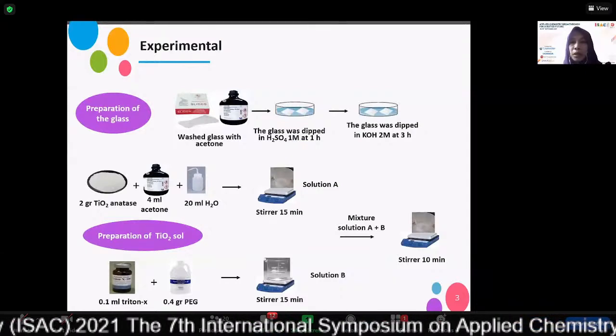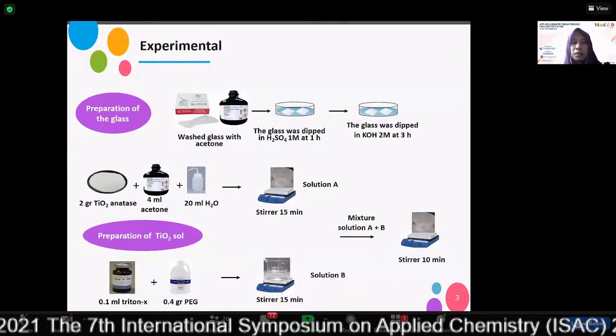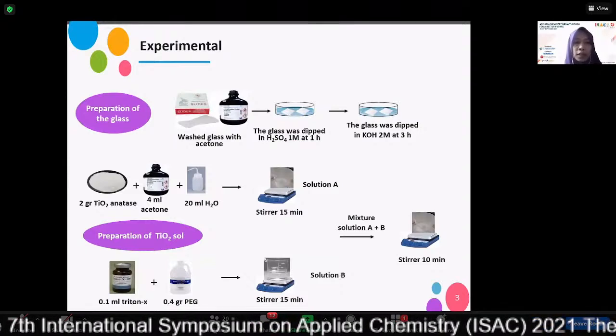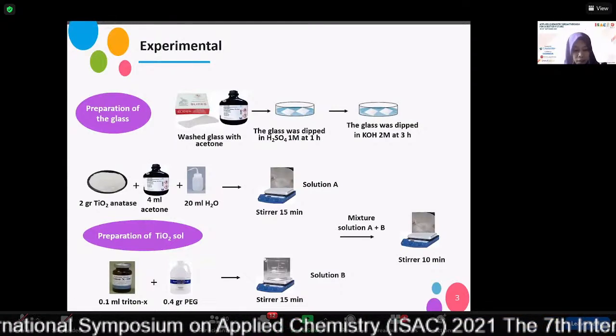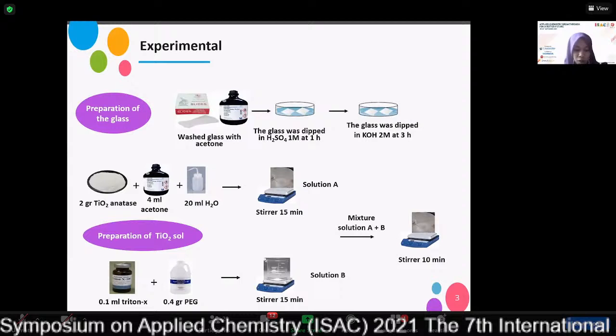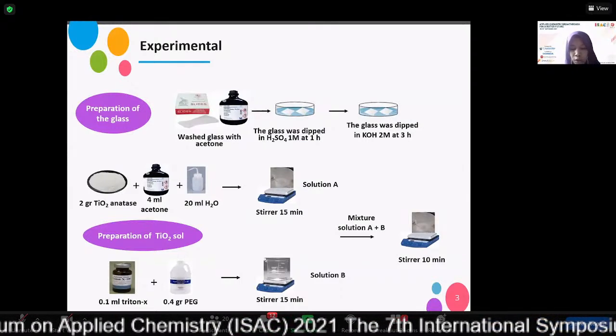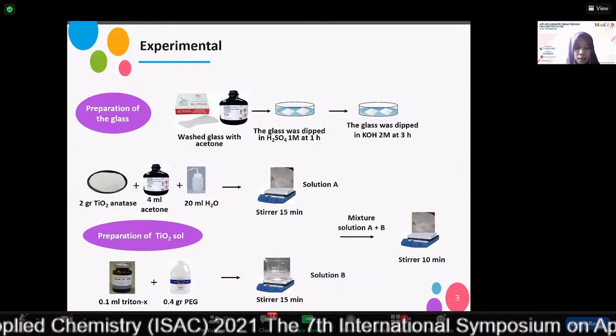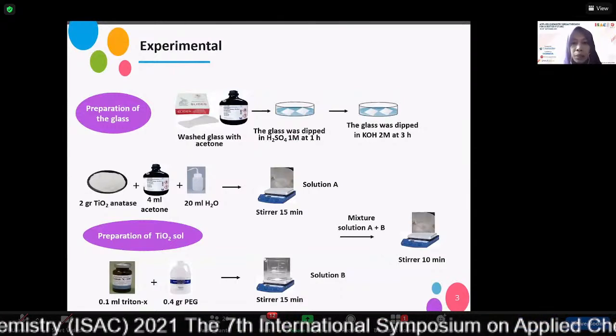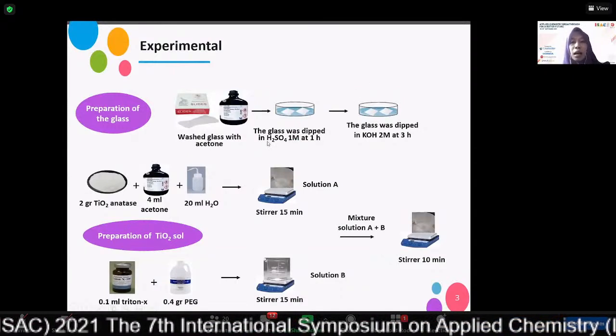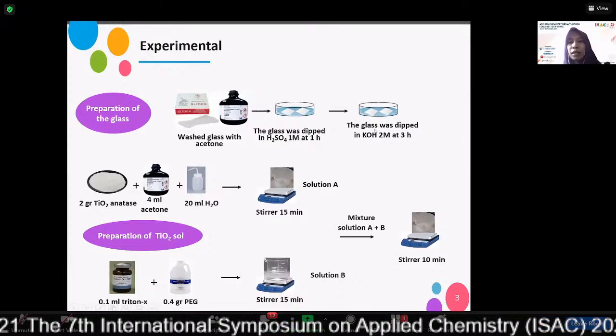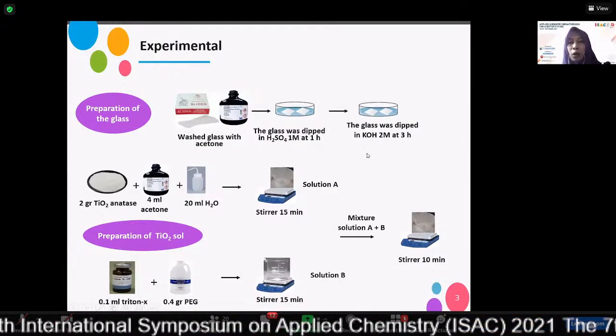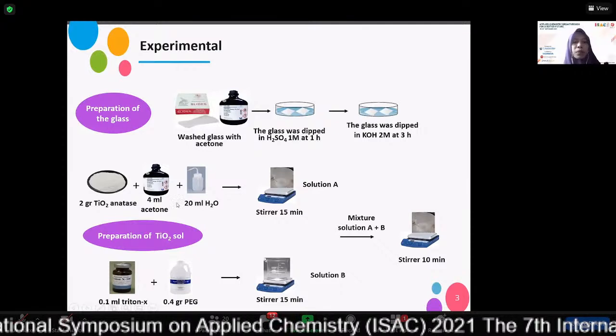First is the experimental method. There are several steps. First one is preparation of the glass. All the glasses were washed with acetone, then dipped in H2SO4 and then dipped in KOH for 3 hours.